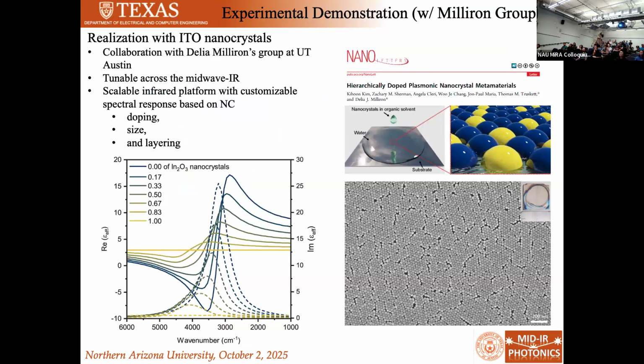But we were working with Delia Milliron's group in chemical engineering, and she has, interestingly enough, these plasmonic nanocrystals. These are tin-doped indium oxide, and she can control the diameter and the doping, so the number of free carriers in them, and they behave like localized surface plasmon resonators. And it turns out when you deposit them in a monolayer, what you effectively get is a collective excitation of these surface plasmons. And their absorption looks pretty similar. This is epsilon double prime.